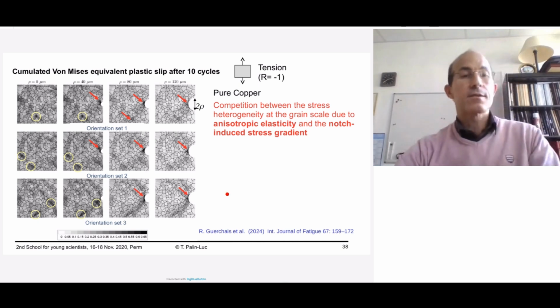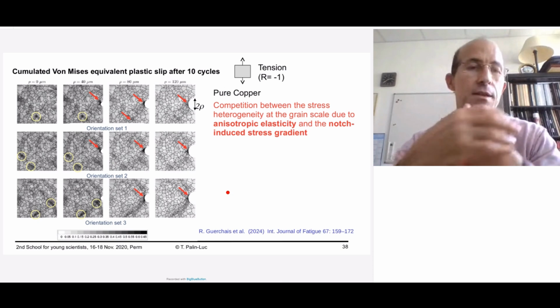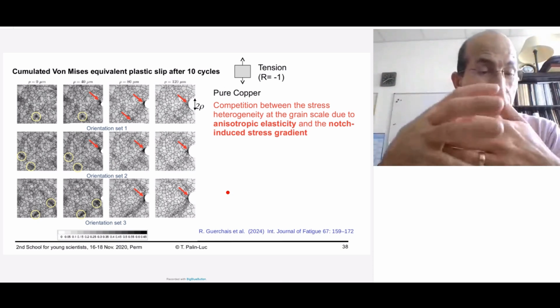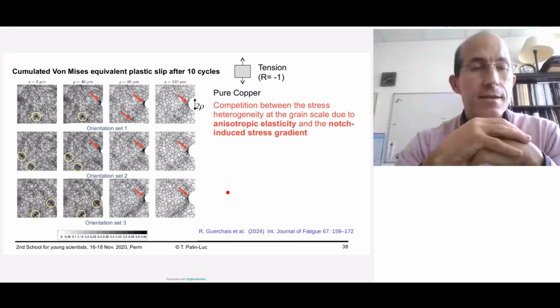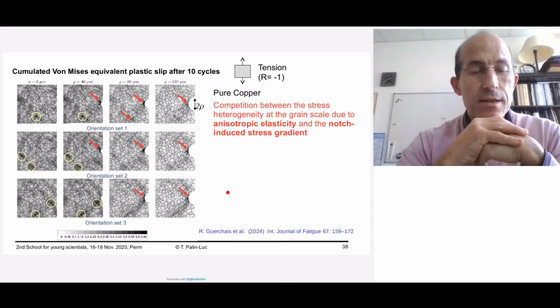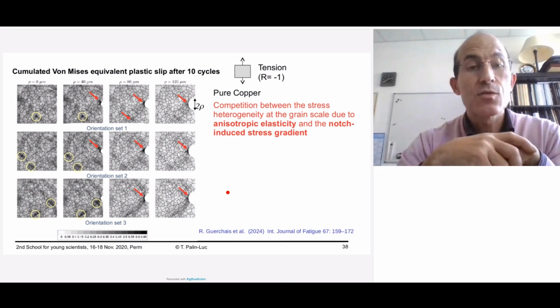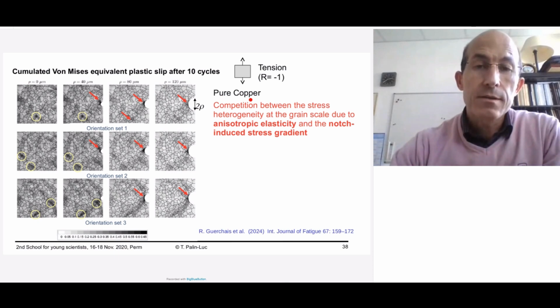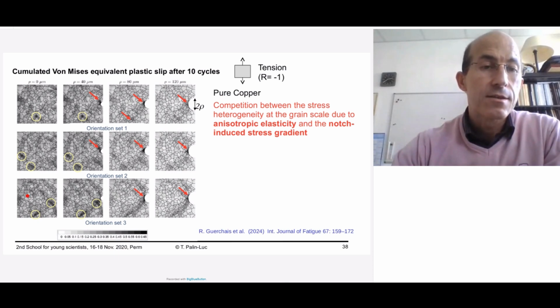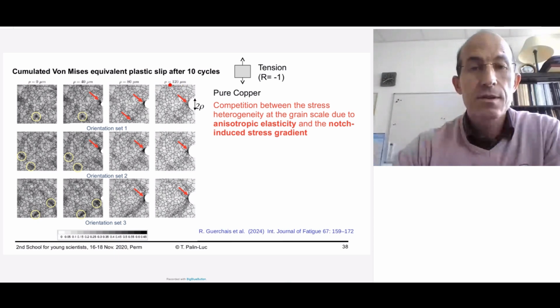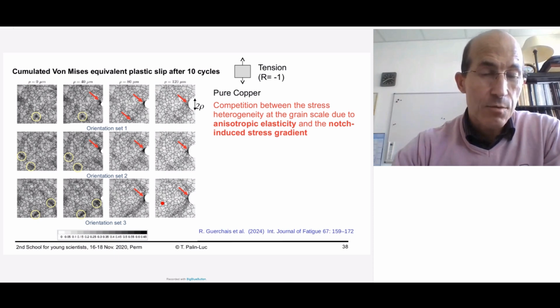The results are the following. This is interesting in order to see the competition between the microstructure, localization of persistent plastic slip or plastic strain, and the localization of the plastic strain due to the defect. So on a pure copper, so a single phase material, you can see here 4 columns, without any defect on the left, and on the right with a large defect with radius rho equal to 120 micrometers. And you can see that the higher the radius of the defect, 40, 80, or 120 micrometers, the less heterogeneous is the cumulated plastic strain.